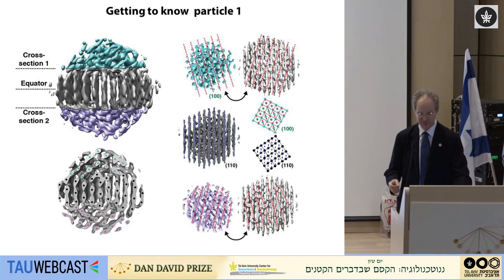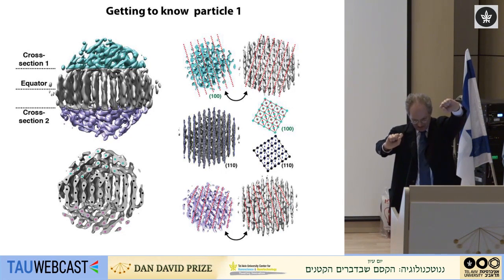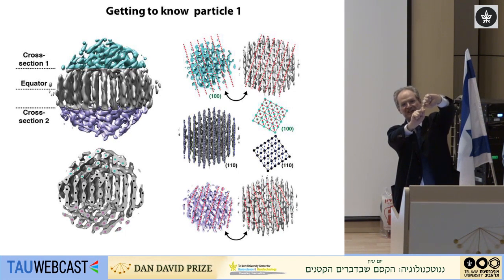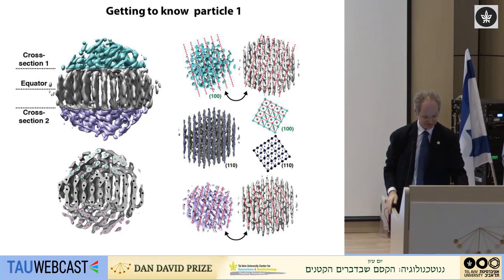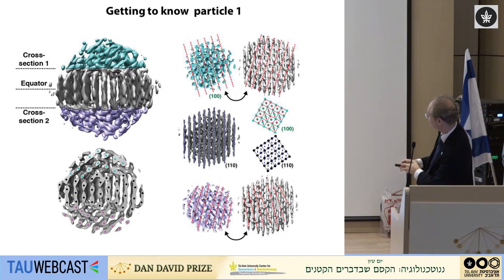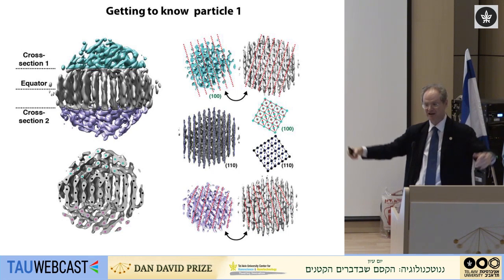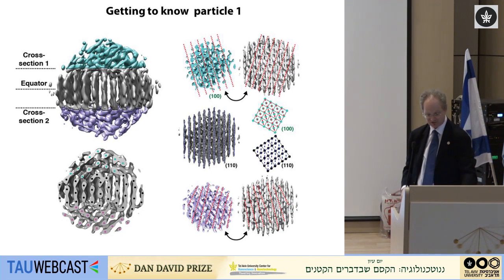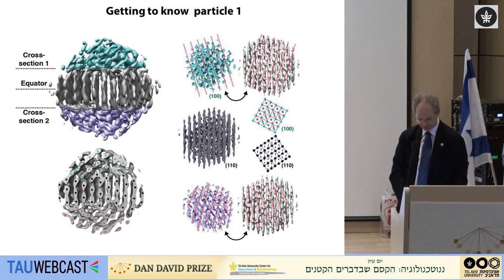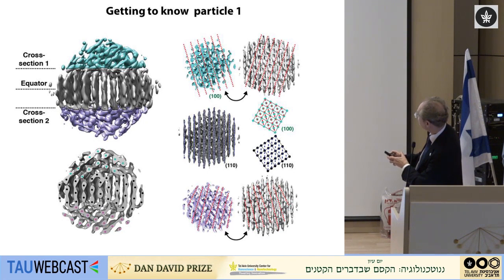And in fact, what happened in this particular crystal is that a 110 and a 100 face collided at an asperity at a single point, and then atoms filled in around from the sides. We could see that in the movies, and then they made a flattish surface, but in fact the grain boundary, if you move all the way through the crystal, actually has roughness and fluctuates inside of it. It's not a completely flat grain boundary the way you might think it would be if you could only look at a single projection. Now, this is not quite yet good enough to obtain the positions of the atoms here at the surface, but it's close.